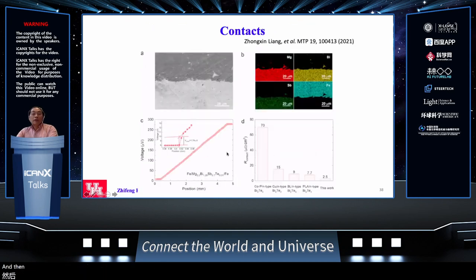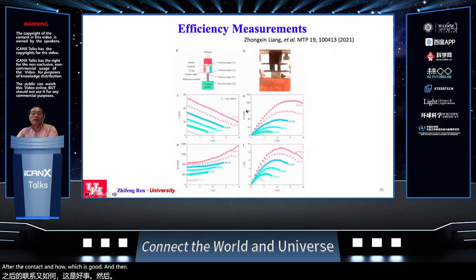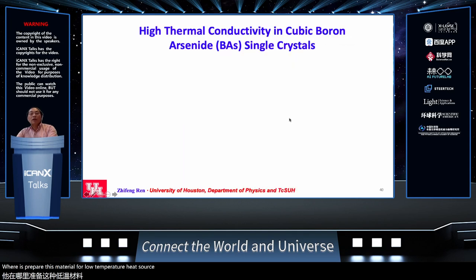And then we did the contact. We showed that the contact resistance is pretty small, only about 2.5 micro ohm square centimeter, and without too much interdiffusion at the boundary of the contact and the thermoelectric materials, which is good. And then we did the measurement of the efficiency and output power. Here it shows the efficiency is about 9%. The hot side is only 300 degrees C, which really prepares this material for low temperature heat source recovery.